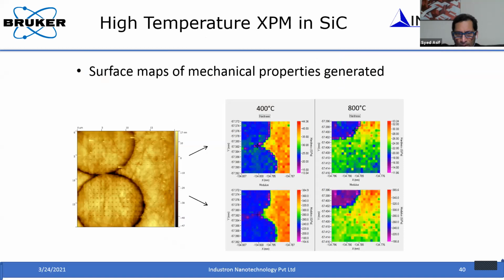So let's look at silicon carbide. This is again, like I already presented, for room temperature. In the silicon carbide matrix material, the fibers are also silicon carbide, and the matrix is also silicon carbide. I mentioned that we wanted to study as a function of temperature as well as how the property is changing across the interface, that you can see clearly at 400 degrees C as well as 800 degrees C, in the hardness and modulus map. Okay.